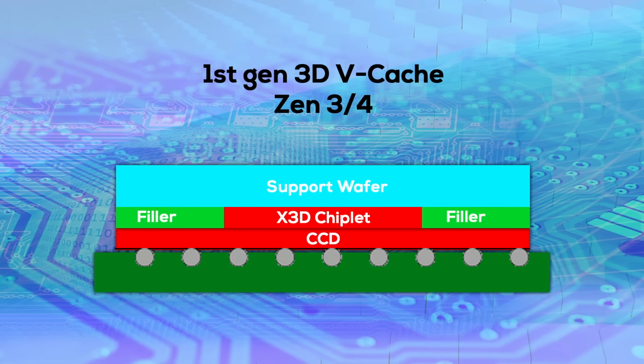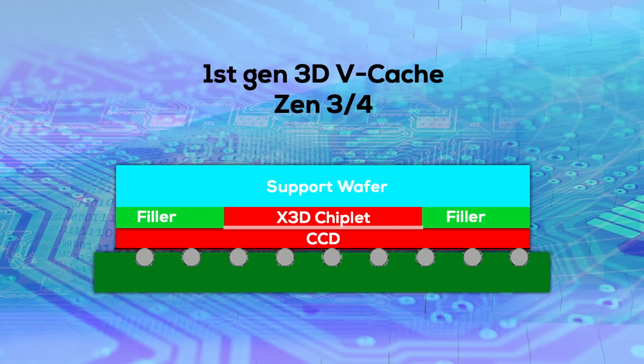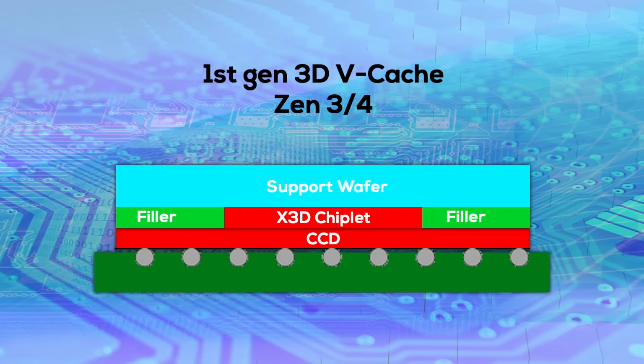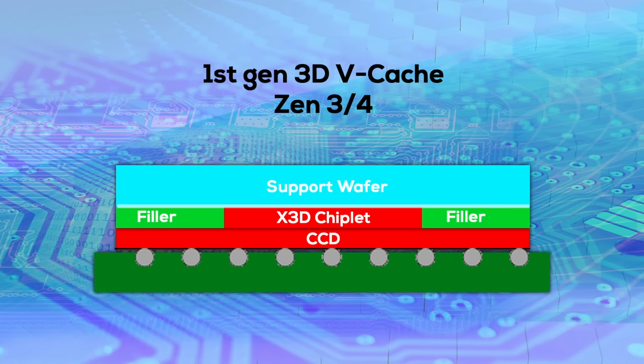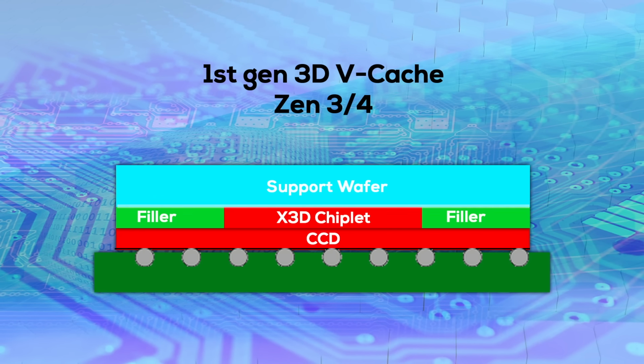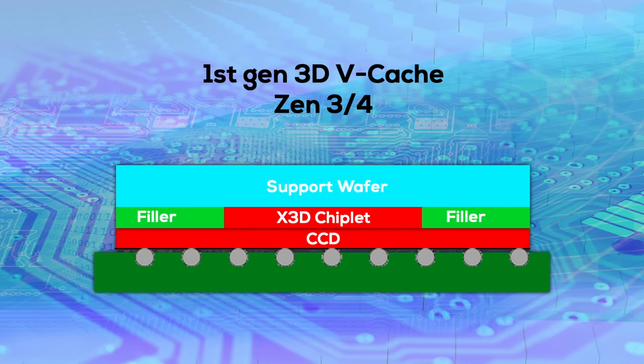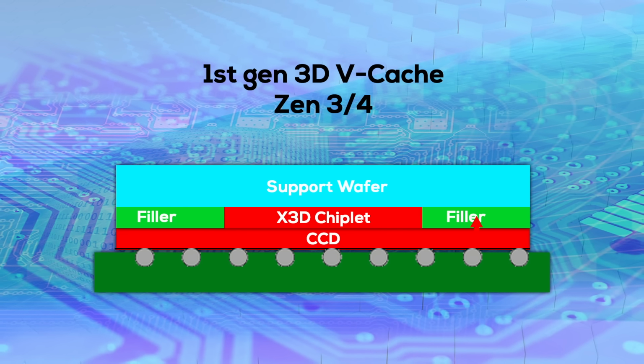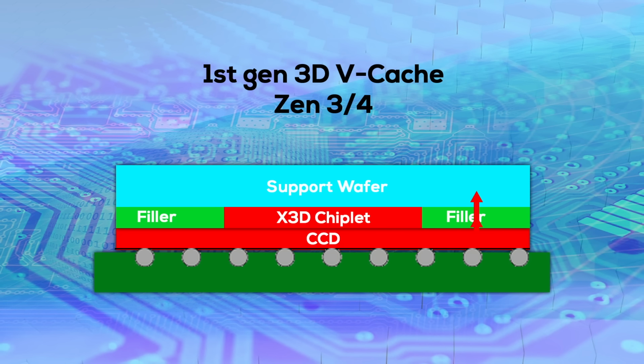Only the small area between the CCD and the cache chiplet uses hybrid bonding, as in dielectric material and copper. The other areas, and that includes the entire bonding layer of the support silicon, only uses a simple oxide layer. That means the heat from the CPU cores on the CCD has to go through the oxide layer between the CCD and the filler silicon, and then through another oxide layer between the filler silicon and the support silicon.